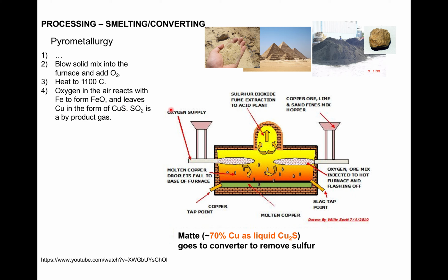Some of the sulfur is vented out of the top of the smelter as sulfur dioxide because some of the sulfur in chalcopyrite reacts with some of the oxygen in the air that we're pushing in to produce sulfur dioxide. The silicon dioxide from our beach sand up here, center top left, reacts with limestone, which is calcium carbonate, and FeO, or the iron, to form a liquid that we call slag, which is composed of iron, silica, and oxygen, and calcium, silica, and oxygen.